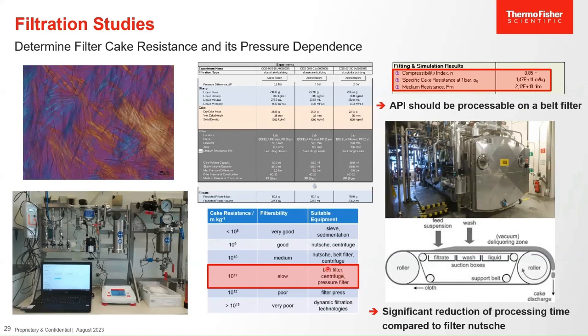But since this material is compressible as well, and centrifuges are a poor choice for compressible materials, we opted for a belt filter. You can see an example of a belt filter here. Why do we use a belt filter in such cases? The cake that we generate on the belt filter is very thin. And any issues due to compressibility of the cake, due to high thickness of the filter cake, tend to be mitigated by the thin layer of cake on the belt filter. Typically, we're talking about 5 centimeters maximum on a typical belt filter.